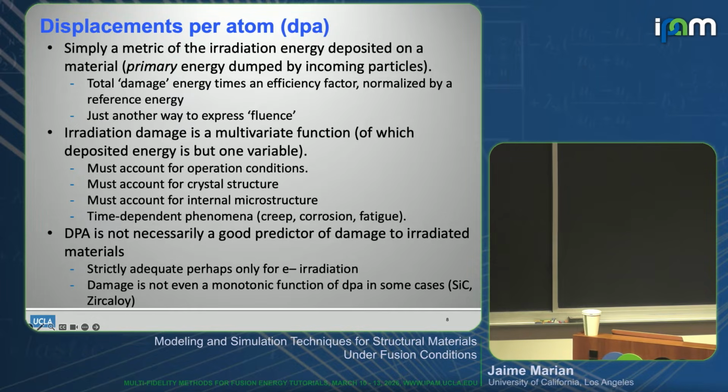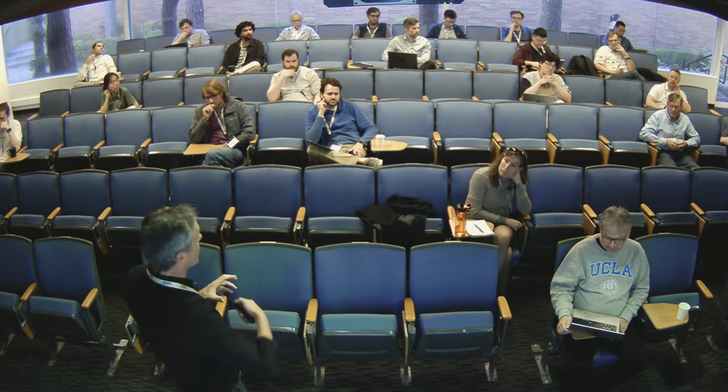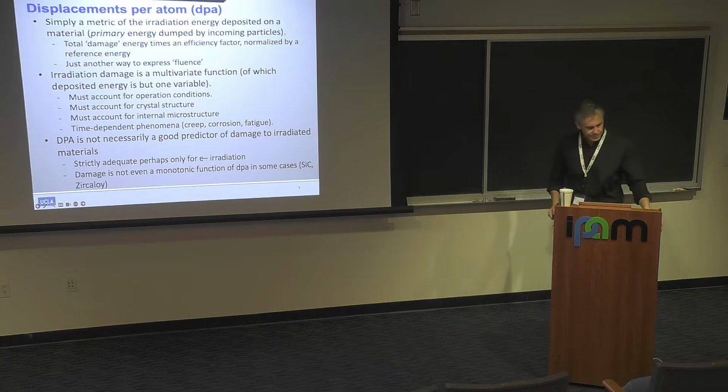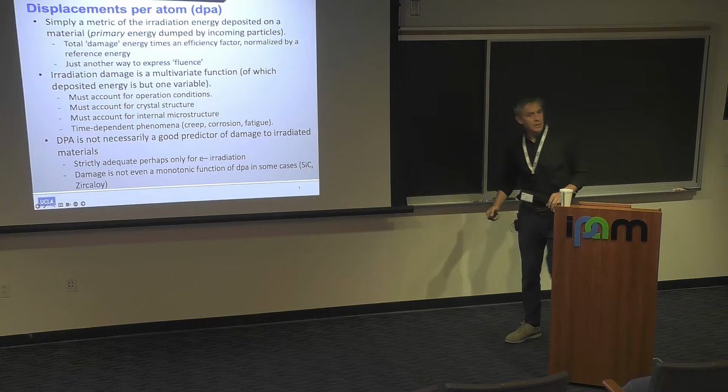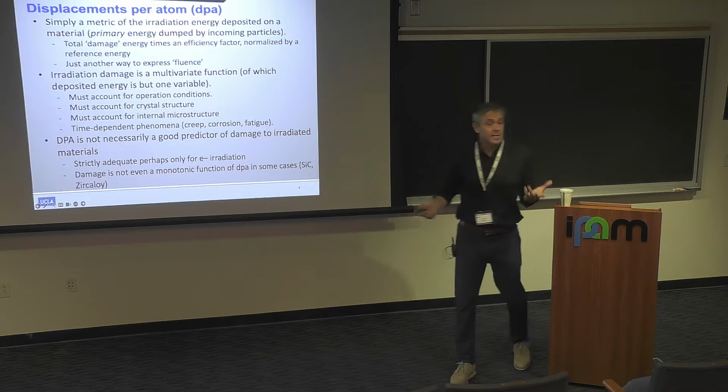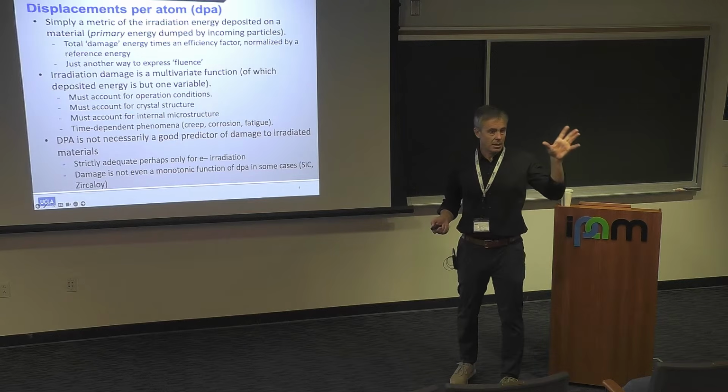Doesn't it matter how far it's displaced as well? So 1 dPa assumes that it's been displaced far enough that it loses memory of where it came from already. So that's sort of embedded in there. Yeah, that's right. It's an irreversible displacement. Is it a time integrated quantity, or is it like a rate of per year? It's basically time. It's integrated over a lifetime.